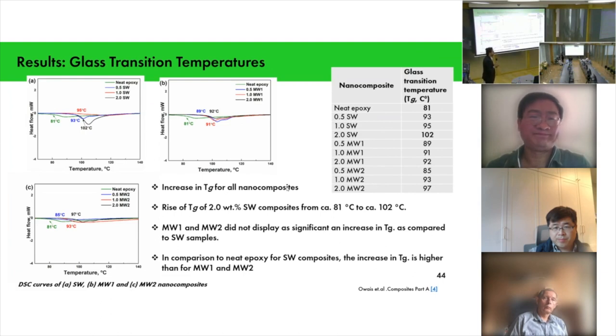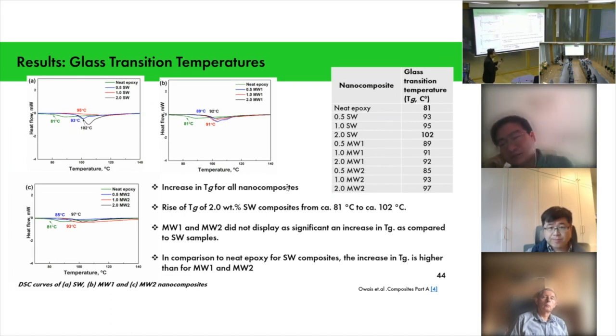Okay. You induce fibers inside, and if you have high density fibers at high aspect ratio, at the transition temperature from the glassy state to the rubbery state, you are actually impeding the polymer segmental mobility. So that can be the reason: the high aspect ratio, interconnectivity with homogeneous mixing.